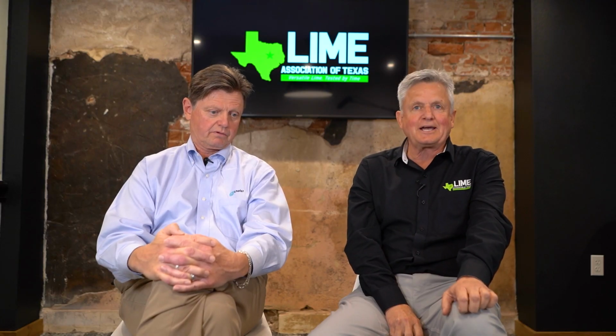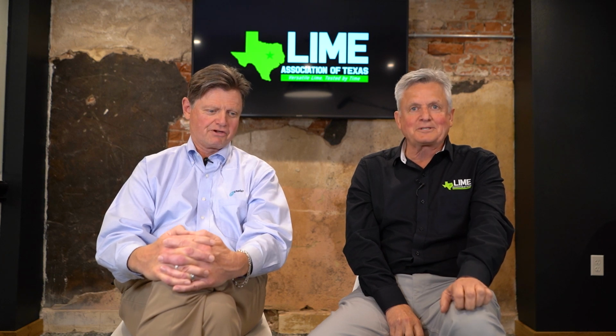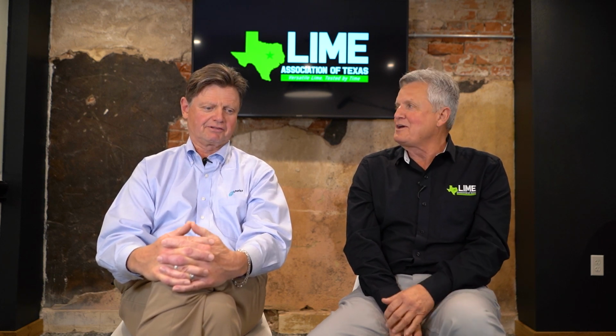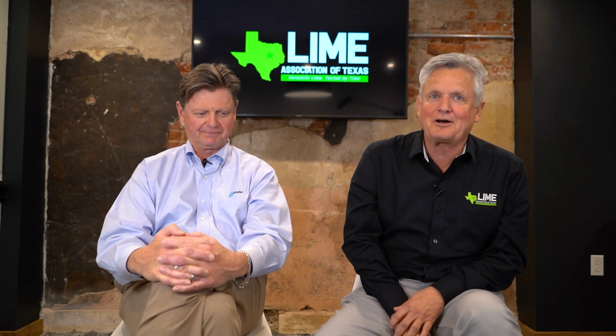As you get into extremely fine grain materials, which is what clay is, that's where lime will work. So if you put lime in a material that's got a PI of 5, you're not going to get anything out of it. In fact, you may call your salesman and say, hey, this lime is not working. Well, we'll tell you lime does not work without silica and alumina in combination with it.